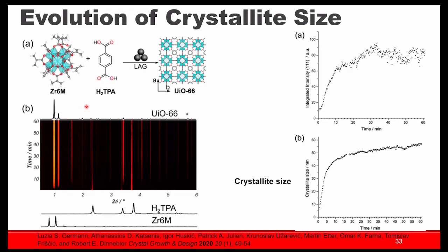One of the other factors that we've looked at in terms of ball milling is a change in crystallite size. This is something that always really surprises people, that you can make crystalline materials in a ball mill. And it's very counterintuitive, because usually you try and smash crystalline materials and get them amorphous, like I previously showed. But if you're using liquid assisted grinding, you're actually able to make really, really crystalline materials.